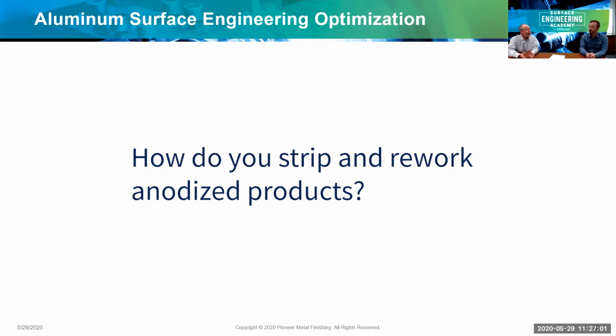So to re-anodize, we have to get back down to the raw aluminum. If we're going to remove the coating, we have to take all the coating that was penetrated into the base metal off. Now the size of the part has changed because of that. And there's also a maximum amount of anodizing that can be put back on a part because of the fact of it being a non-conductive coating. In general, 3/1000ths, depending on the alloy, is about the maximum that can be grown back on the part.